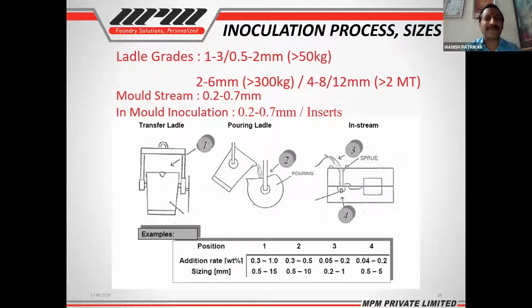So this is a normal practice. I would suggest everyone has to establish their own numbers, but whenever somebody is talking about ladle grade inoculants, the ladle grade inoculants are ranging from 0.5 to 2 mm, 1 to 3 mm, 2 to 6 mm. There are always some questions people are asking: what ladle is the best? What sizes are the best for the sizes of the ladle? So this is in general. Everybody has to set their own parameters, because no foundry is similar, even though they are producing the identical component.